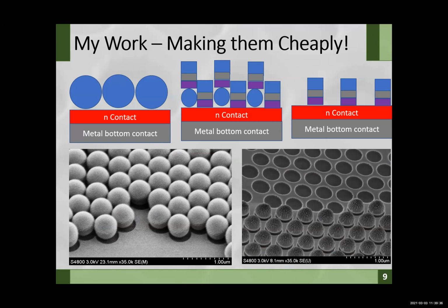One of the ways we do it is we use the self-assembly of polystyrene nanospheres, which you can just buy, and if you deposit them in exactly the right way, then you can form a perfectly close packed layer, which you can then use as a mask to make these honeycombs, which are about 500 nanometers across. And so this is one of the ways we are looking at trying to make them cheaply.